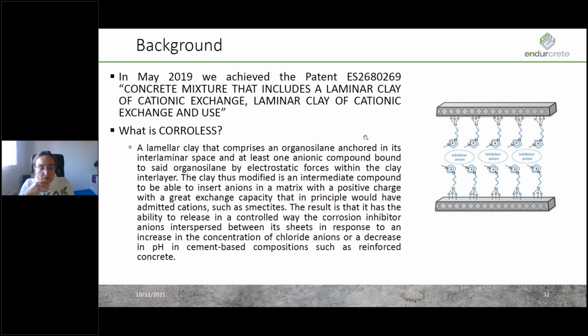Within EnDurCrete, the objective was to develop a product that will act as an intelligent reserve of corrosion inhibitors in reinforced concrete, which can be released only when there is a danger of starting the oxidation processes of the reinforcement. The fundamentals of these inhibitors, which we call Corroless, is that they are laminar clays modified with silane groups and anionic corrosion inhibitors for the prevention of corrosion in reinforced concrete. These additives respond actively to the presence of chloride anions, which cause corrosion in concrete, releasing the inhibitor anion in the presence of high concentrations of chloride anions through an exchange mechanism.